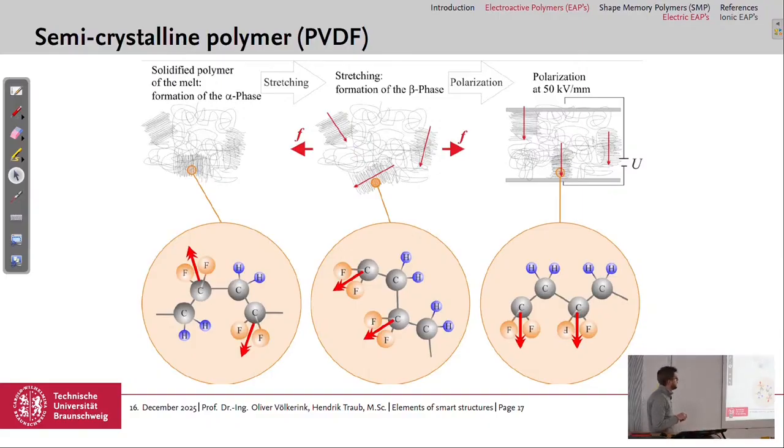And by doing so, we reached the melting temperature of the PVDF. So we have lost the polarized beta phase, and we're at the alpha phase. And the integrated material in the adhesive joint in the structure, we were not able to stretch it again, and only polarization didn't work out. So that was the idea to use it, but it didn't work.